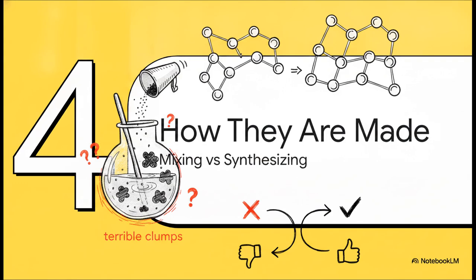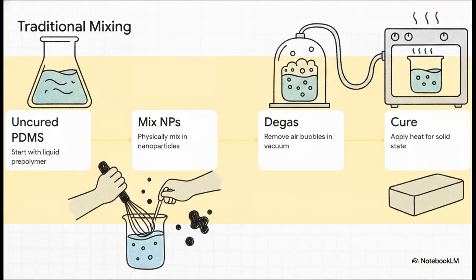Which brings us to Section 4, how they are made, mixing versus synthesizing. So how do we get the magic dust into the rubber without causing those terrible clumps? Well, the traditional method is called ex situ mixing, and it's essentially like baking a cake. You start with liquid, uncured PDMS prepolymer, you physically mix in your pre-made nanoparticles, maybe using some solvents or a mechanical stirrer, then you put it in a vacuum chamber to degas it, pulling out all those trapped air bubbles. Finally, you apply heat to cure it into a solid state.